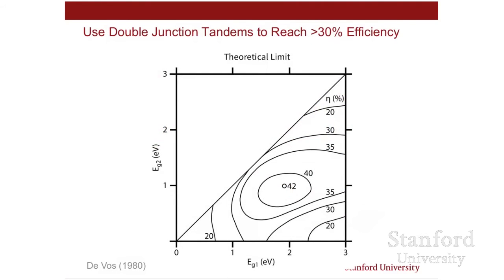This plot here just shows the efficiency you can get as a function of the band gaps. On the y-axis is the band gap of the low band gap cell. The x-axis is the high. You can see there that 42 is possible, and it tells us that for this application, the band gaps we want are about 1.1 electron volts and 1.8. So some numbers to keep in mind as I go forward: for single junction, we want 1.4 eV, and for two junctions, we want 1.1 and 1.8.